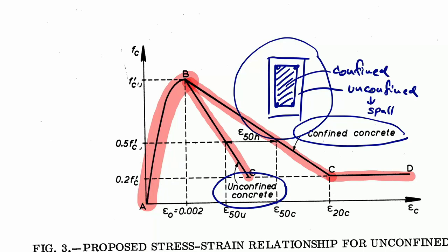So the point is that many times in your research, you might need to use the elastic modulus of concrete at the low stress level. It is not like steel. Steel has a constant E throughout the elastic range, but for concrete, E keeps changing all the time. For the initial slope, it does not change much, but once you go up, you can see the slope changes rapidly.